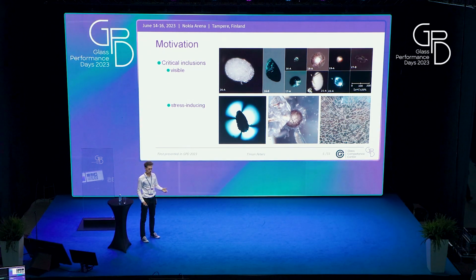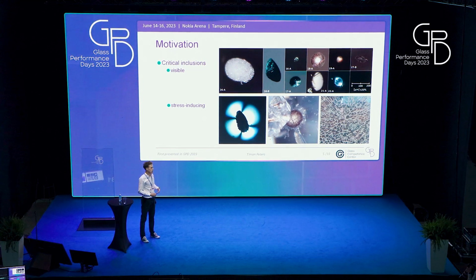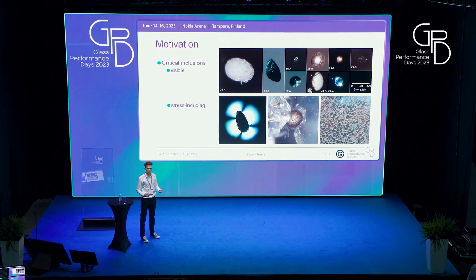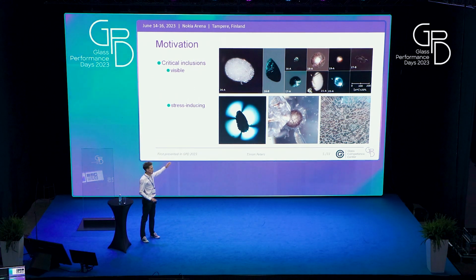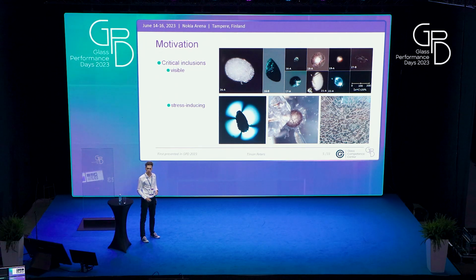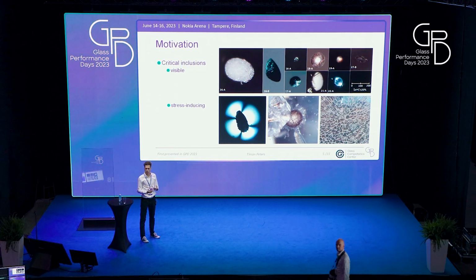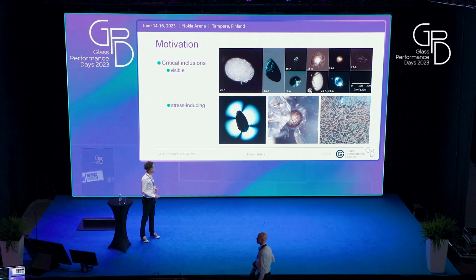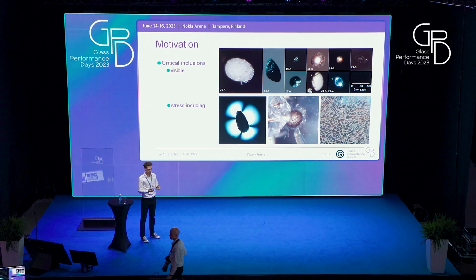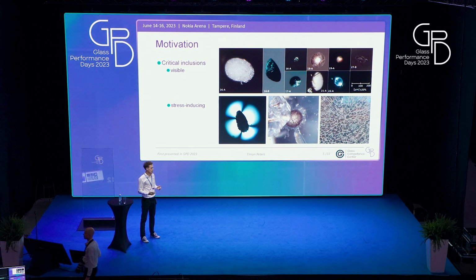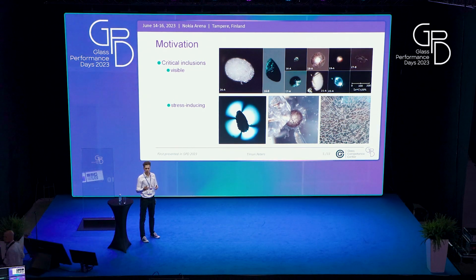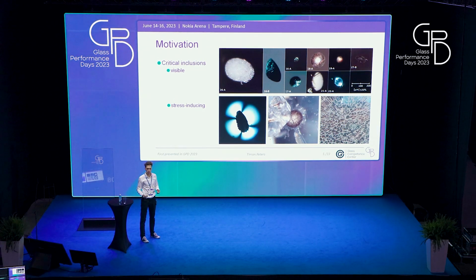But what's even worse is inclusions that create enough stress in the glass to make the glass break, especially if it's tempered. On the left one, we can see our standard zirconia stone that is created by the dissolution of the glass melting furnace itself. This one usually creates stress immediately, and it will lead to failure of the glass immediately during pre-stressing.